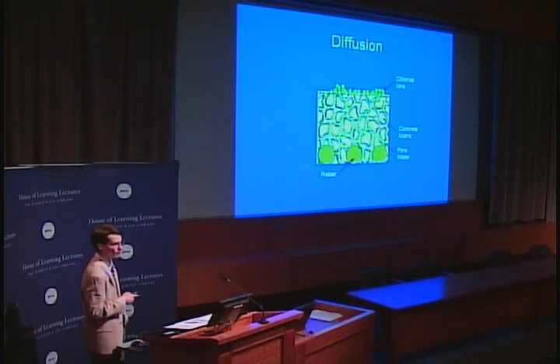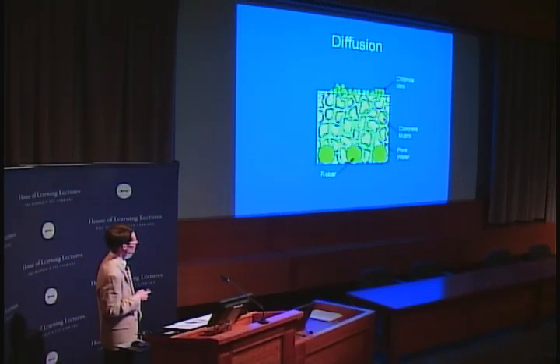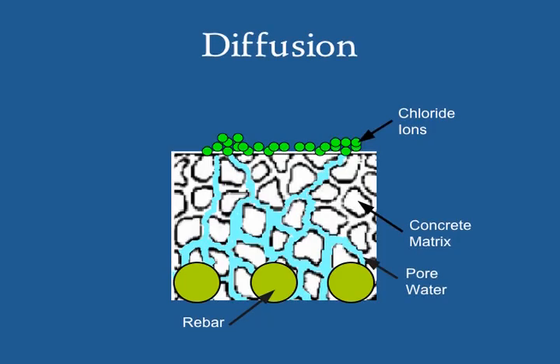We're looking at the side profile of a bridge deck, the upper 2 or 3 inches. This is the top mat of reinforcing steel, or rebar. Concrete itself is composed of gravel, sand, and cementitious products. The cementitious products are the result of the hydration of cement, a white powder, which is added to concrete to cement the sand and the gravel together. Concrete has an internal void structure, which in most cases is at least 90% saturated. The concrete pore water provides a pathway for the chloride ions to enter the deck. As the ions approach the rebar, they can then cause corrosion of the reinforcing steel.